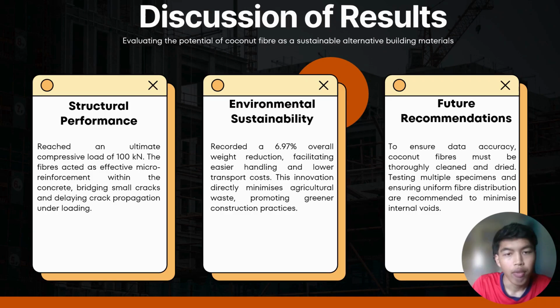The incorporated fibers act as micro-reinforcement which bridge small cracks and delay crack propagation. Furthermore, the fabricated brick met the specified dimensions flawlessly. This finding suggests that the brick possesses adequate strength for lightweight or non-load-bearing construction.